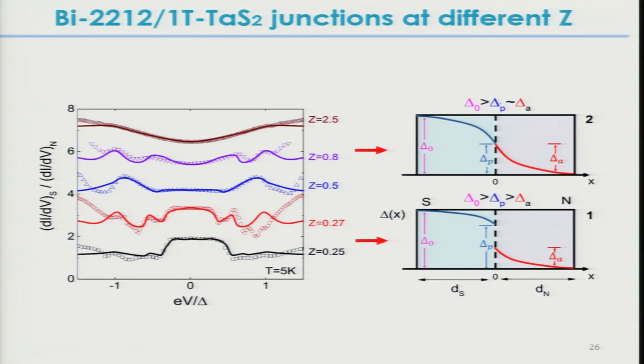And the proximity effect is measured by the doubling of the conductance in this region for a high transparent barrier. Low Z means high transparency. And what we are measuring from the structures in our current voltage characteristics are these energy gaps. This is deep in the superconductor. We have the bulk Bisco gap. The gap is reduced to a certain value at the interface. And then there's a gap that's induced. There's a discontinuous jump, and a gap that falls off into the tantalum disulfide.